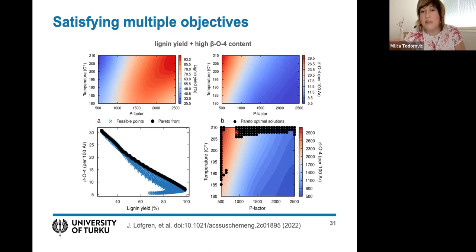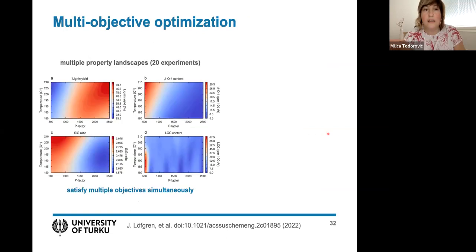And you can map this Pareto optimal solution back onto the phase space of the experimental variables. And you see all of those points lie on the top edge. And this is because we're looking for solutions that are along the top edge, here on the right and here on the left. And so all the trade-offs lie in between these two. So now we could really do multi-objective optimization.